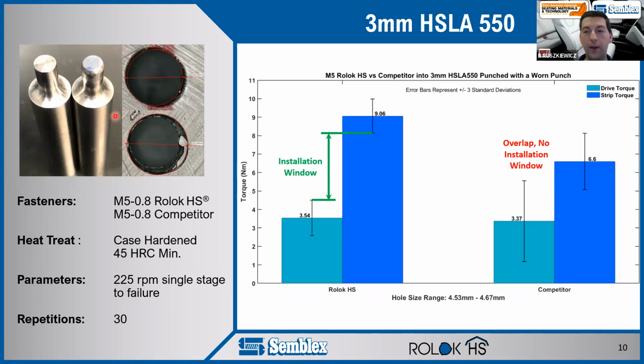Now over here to the left, we mentioned that they were having issues when their punches started to wear. So on the left, we have a new punch with a nice sharp edge. On the right, we have a punch that we took to the grinder and took the edge completely off. This simulated our worn punch and is much worse than what we typically see from any of our customers.